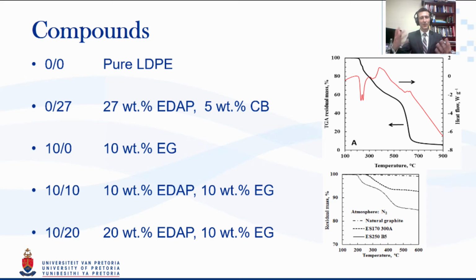So we looked at the thermal behaviors in TGA and in TMA of a lot of these materials. Unfortunately, EDAP was not one of the materials that we could do TMA analysis on because with thermomechanical analysis, the probe in this case would go into a softening or expanding event depending on the atmosphere that it's in. But that ethylene diamine phosphate becomes extremely glossy and it would actually damage the probe. So unfortunately, we couldn't do that, but we did verify with a few other methods that it would work in terms of reacting at the same time as expandable graphite so that their layers can expand into one another.